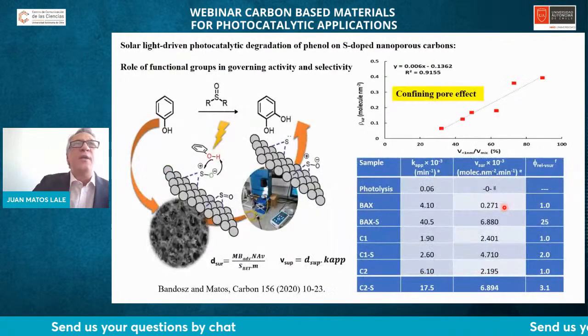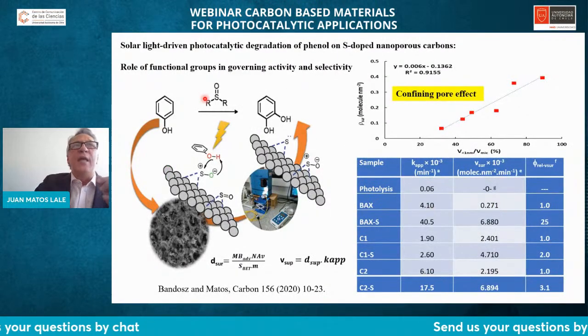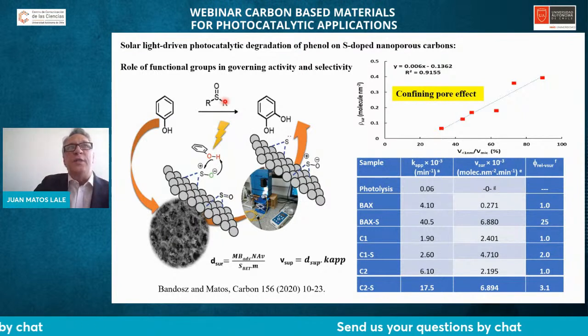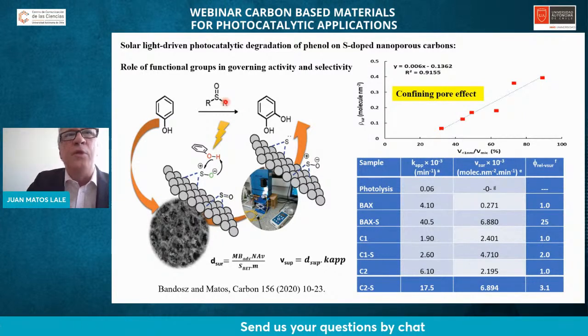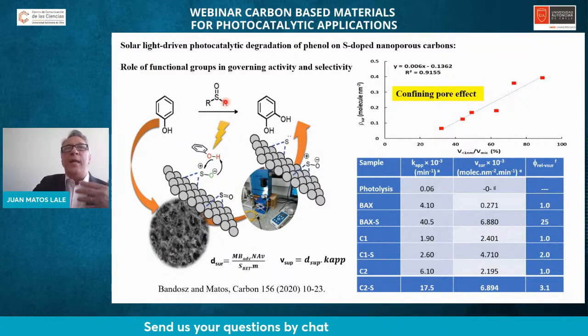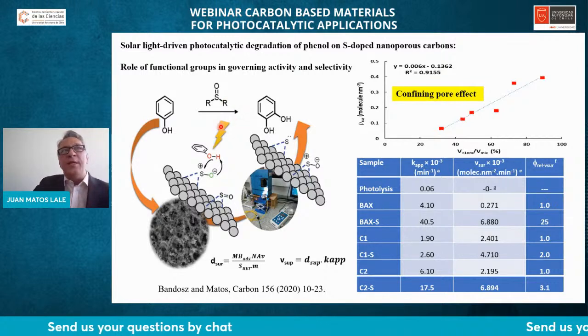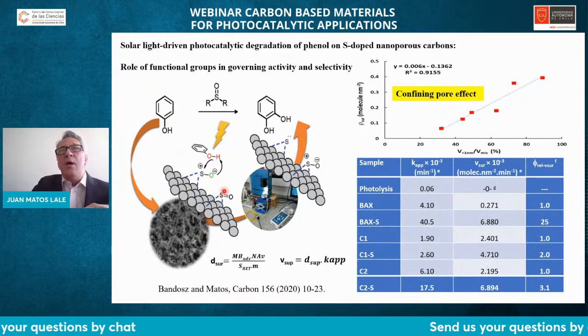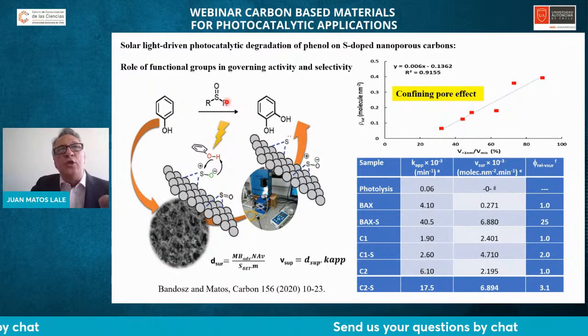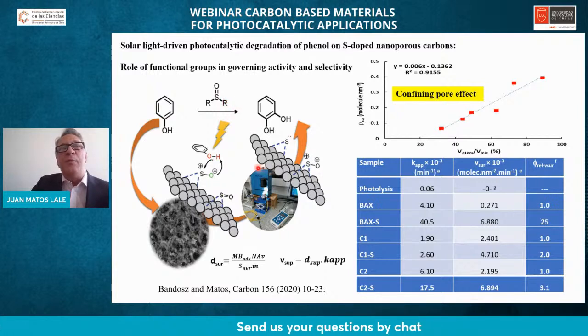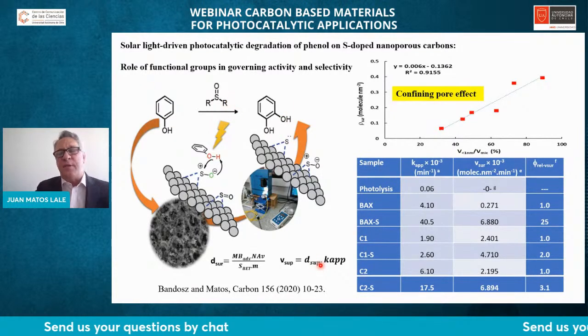In other words, we demonstrated, for example, that reduced sulfur oxidation states are able to control the selectivity of product, and instead of having sulfates, we use sulfoxides. We are able to control the formation of catechol from phenol. This is a recent work.